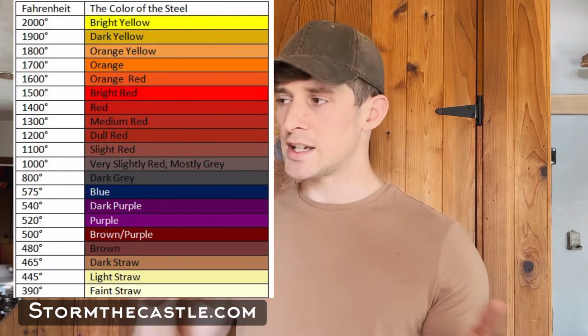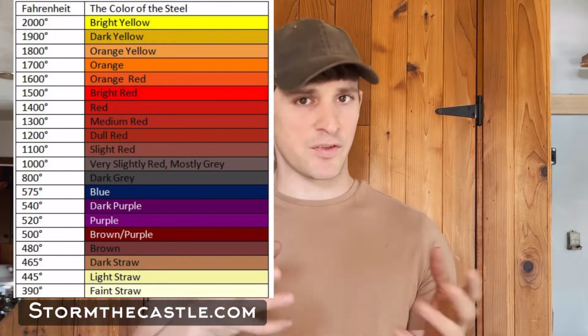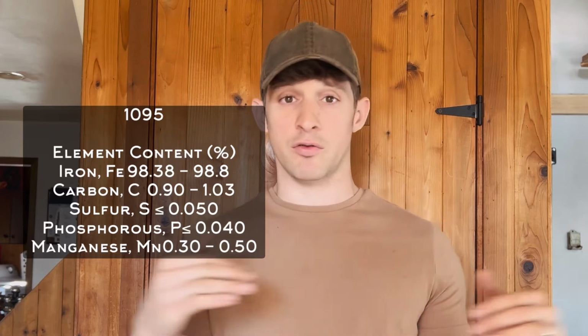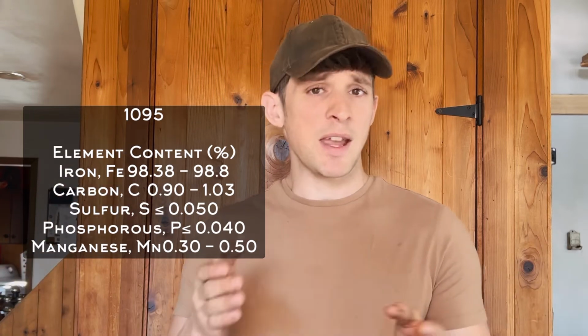Now, it is true that there's a lot of differences in the way that different types of steel react to heat. For instance, 1080 steel is more forgiving under the heat, whereas 5160, I have found, tends to be a very heat sensitive steel. So you need to take care of it a little bit more. Usually work it on the higher end of the heat scale. You can temper it a little bit higher for various reasons. It has to do with the components that make up that individual alloy. But we don't need to get super specific. We'll be using 1095 steel, which is a great steel for both beginner and advanced smiths. In fact, some of the best blades are still made out of 1095. So we're just going to go nice and simple, straightforward.